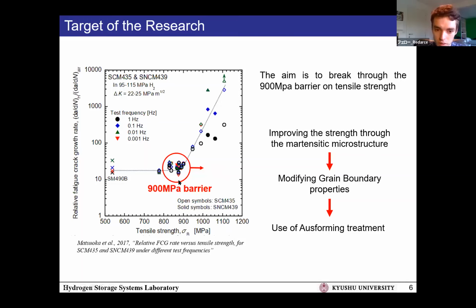Here we have this 900 megapascal barrier. It's with these two metals. If with them we have a design, for now it's the typical microstructure we get from heat treatments. If the strength is over 900 megapascal, it will be on this part of the curve. But with this other way of treatment, the ausforming, we may be able to have metals that have a different structure. Even if their tensile strength is over 900 megapascal, the fatigue crack growth rate will stay in this general area. Okay. If we are able to be there, it means that we can actually design very high capacity containers. Okay, I understand.